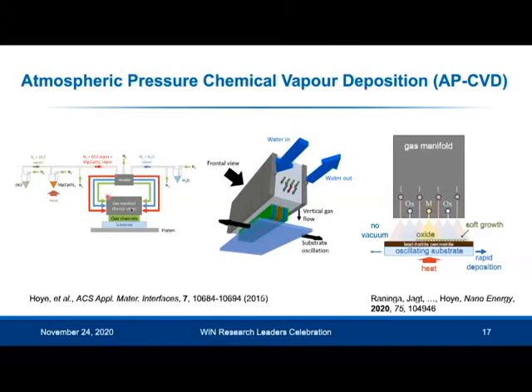So in this reactor, we have some liquid precursors. These can be the same precursors as in atomic layer deposition. You bubble through them using an inert gas, which carries them to this gas manifold here. So here's a 3D sketch of the gas manifold, and the precursors are introduced from both the right-hand side and the left-hand side, and there's a header channel running through it, which guides the gases to go vertically down to the substrate, and you move the substrate backwards and forwards to grow the oxide layer by layer.